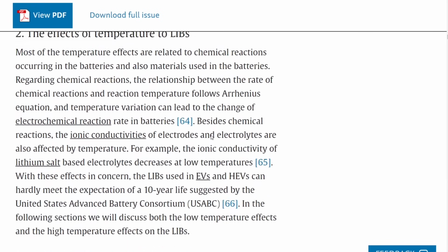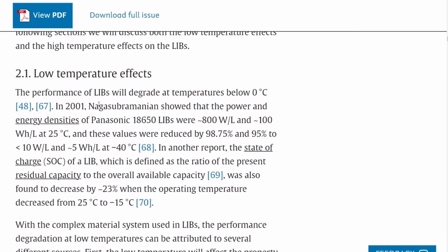So what are the effects of low temperatures here? There was a paper in 2001 that showed that the power and energy densities of these 18650 lithium-ion batteries from Panasonic dropped by almost 100% when you drop their temperature to -40 degrees Celsius. Now, -40 degrees Celsius is quite cold. I believe that's like -40 degrees Fahrenheit as well. That's really, really cold, and those are temperatures not normally reached in most cities in the world, most places where people live. Maybe Yakutsk in Siberia reaches those temperatures. But at those temperatures, lithium-ion batteries are essentially non-functional. They're not working. They lose 95 to 98% of their capacity and power delivery.